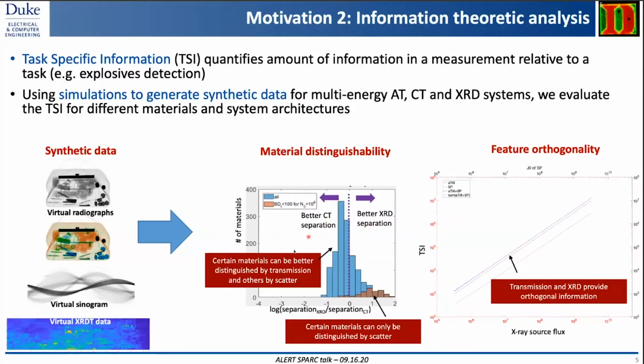So one of the things that we took away is that there's value in each of these systems. Some materials are better distinguished by diffraction, some by CT. In addition, though, we found this interesting point that there were some materials that simply couldn't be distinguished at all in transmission and happen to end up as being reasonably well distinguished via diffraction. So this led us to ask the question, how redundant and how complementary are the different features that diffraction and CT provide? And so Amit's group at the University of Arizona did this task-specific information study where we looked at the amount of information relative to threat detection in a transmission system.